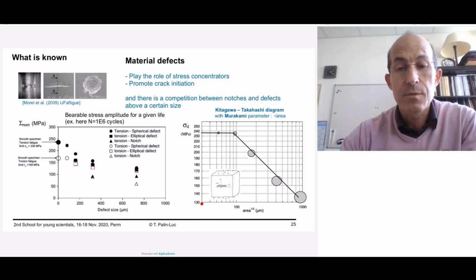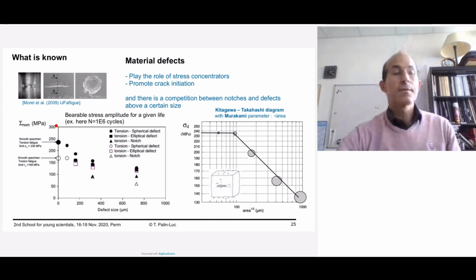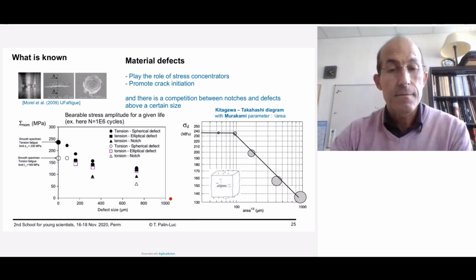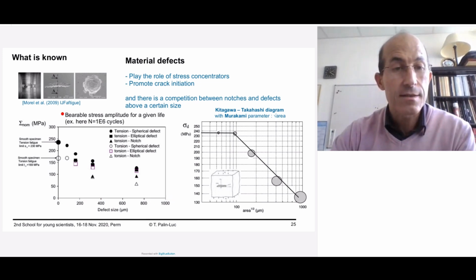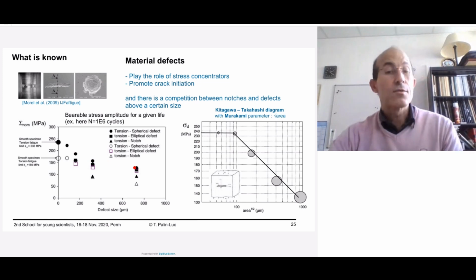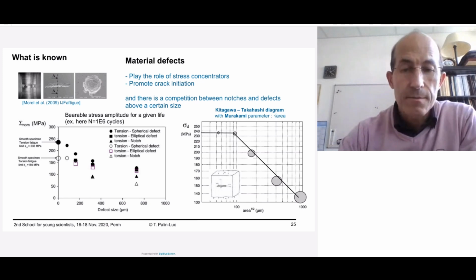And if the defect is small enough, in this example, for a defect size lower than 100 micrometers, you can see no effect on the fatigue resistance. But if you increase the defect size too much, there is a sharp effect on the fatigue resistance, which decreases drastically. This is also illustrated in this diagram with the defect size on the abscissa and the fatigue resistance on the vertical axis. And you see also that when the defects increase, the fatigue resistance decreases. So this is very important for real applications.